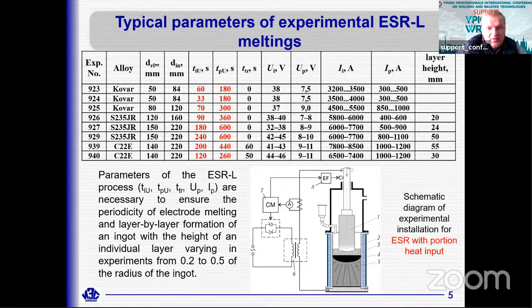This slide shows typical parameters of experimental ESR melting and a schematic diagram of the experimental installation for ESR with portion heat input. Parameters of the ESR process are necessary to ensure the periodicity of electrode melting and layer by layer formation of an ingot with the height of an individual layer varying in the experiments from 0.2 to 0.5 of the radius of the ingot.